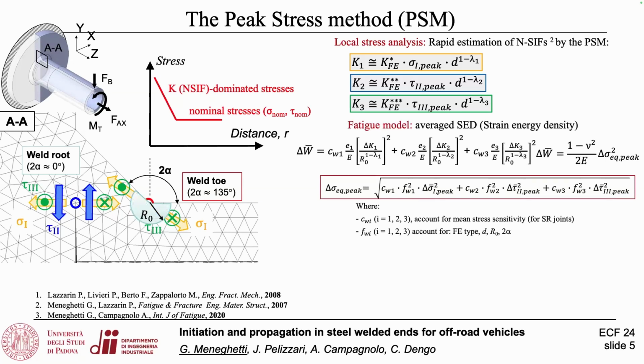Now, going to the fatigue model, this is the model we adopted. Some of you may be familiar with the averaged strain energy density, which takes into account the average strain energy inside the control volume at the critical point, either the weld toe or root. This is the expression based on the notch stress intensity factors.